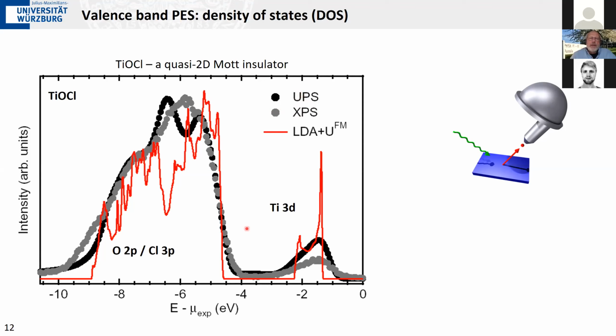But both of these spectra are measured with just detecting the energy distribution of the electrons. We do not measure yet any angle distribution. So we do not look at any k-space resolution here. So in this case, we measure basically the density of states. And as you can see, we have two major structures here in the spectrum. We have these electrons sitting here, which turn out to be the titanium 3d electrons. In fact, it's just one 3d electron per titanium ion in this compound. And we have, which is a typical signature here of oxides, this very strong oxygen 2p, and in this case there's also some chlorine 3p contribution here on the main valence band.